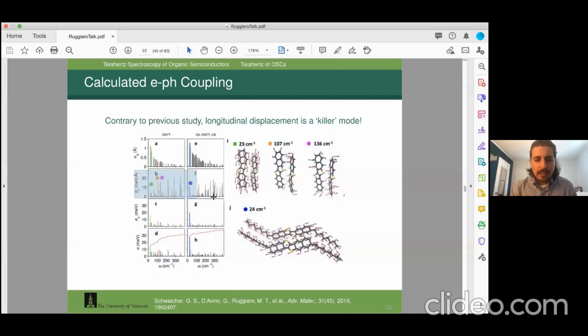What you see here is the unweighted fluctuation in the charge transfer integral on a mode-by-mode basis. So we took each vibration, displaced every mode a constant amount, and calculated the fluctuation in the charge transfer integral—basically how much that motion is going to scatter the free carriers.